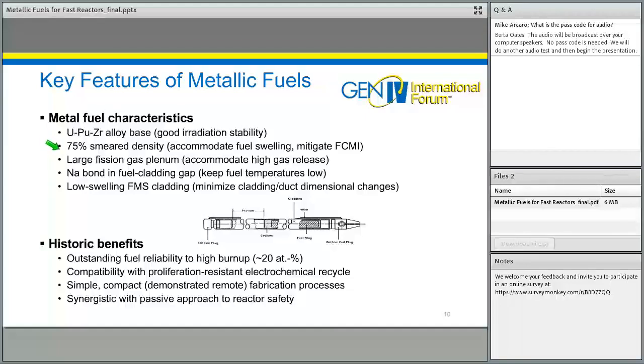Now, one thing associated with metallic fuel is it does swell quite a bit in the early stages of irradiation. Within the first couple percent burnup, metallic fuel will swell 30% quite quickly. After that, the swelling rate decreases dramatically and is not so much of a problem, but you have to be able to accommodate that initial swelling that you get with metallic fuel. And typically that's done with controlling smear density.